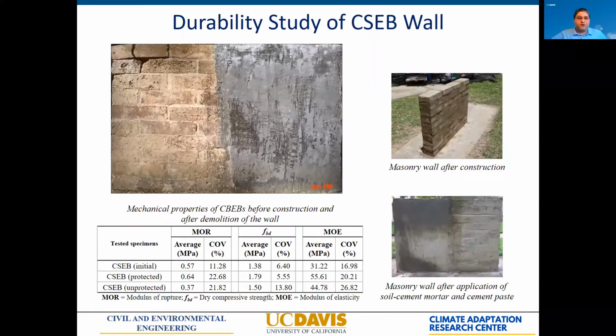And even more, when we dismantled the wall, we tested the bricks that were visually intact. And we found that the side that was protected kept increasing the strength because the cement inside the soil continued actually hydrating while they were subjected to the water coming down on the wall. So in terms of durability, we found a way to make this material very durable, even in hot and wet climate like the one of southern Louisiana.